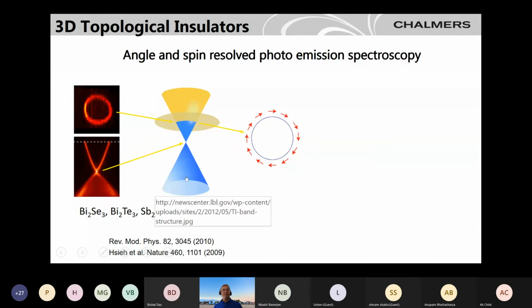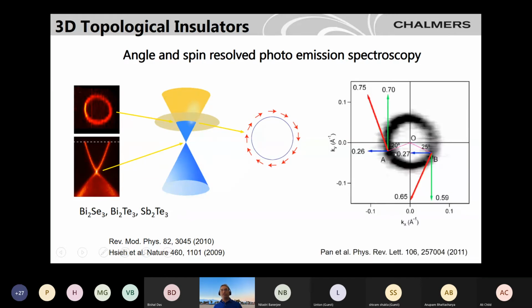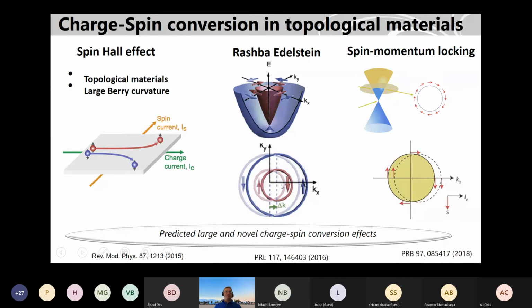Also, people have seen with angle resolved photoemission spectroscopy and spin resolved spectroscopy this Dirac band structure. And when you measure the spin texture with spin resolved ARPES, you can find the polarization at different points here. And this is experimental data, so there is a little bit of deviation at different points. So around 75% polarization. So this can be quite interesting for spintronics, for charge to spin conversion.